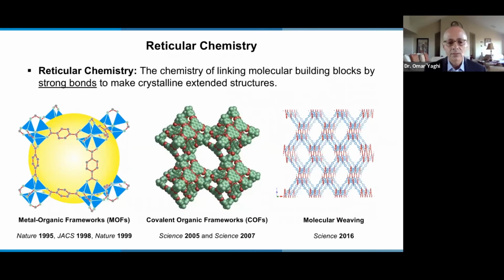For the last 25 years, we've been developing an area we now call reticular chemistry. And in this area, we have produced new materials we call metal organic frameworks, which we showed can be crystallized in 95. And then we showed their porosity in 98. And then we showed their ultra high porosity in 99. We also showed in 2005 and 2007 for the first time that porous materials made entirely of covalently organic linkers, again crystalline, could be made. And through the pipeline, we also have molecularly woven structures. But I will discuss today only the metal organic frameworks. These are made from metal oxide units that act as nodes and organic units that act as struts.